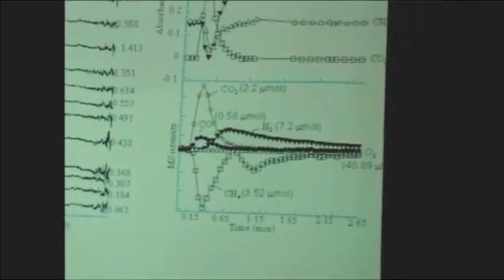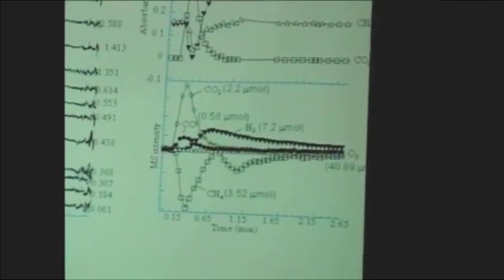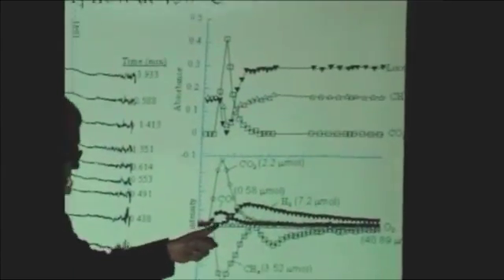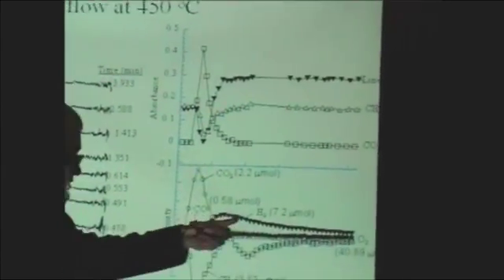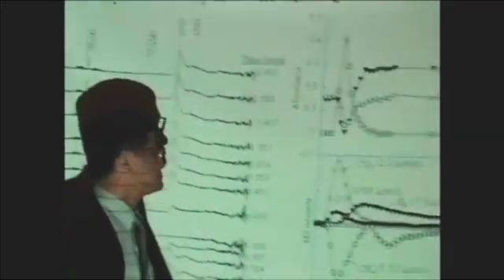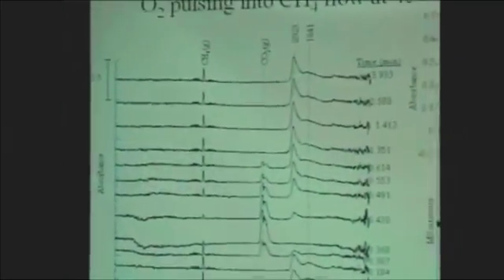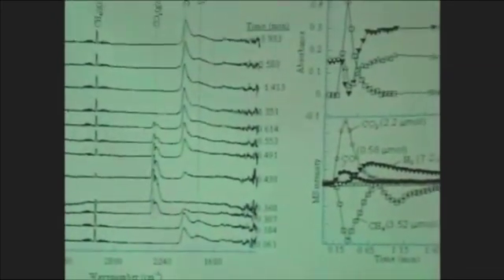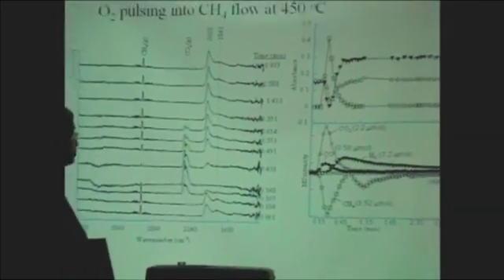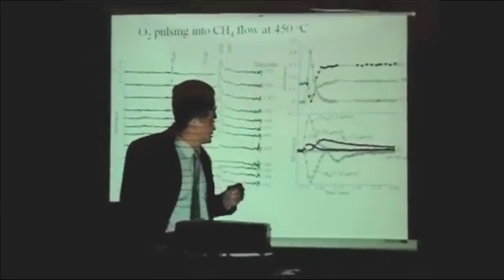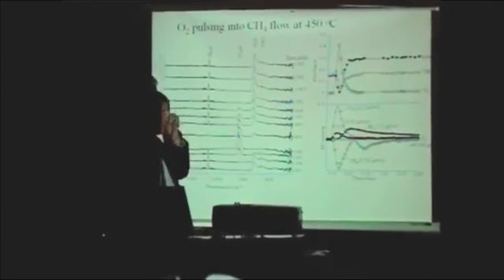So this result clearly suggests that for some reason, hydrogen sticks on the catalyst surface longer than the CO, and hydrogen is slowly produced. And when the methane is activated, the oxygen immediately attacks the C to form the CO. So this is a very interesting result here. Let's compare with the reforming reaction.